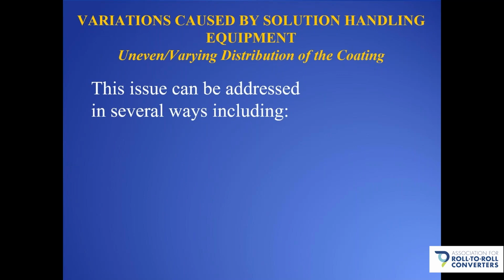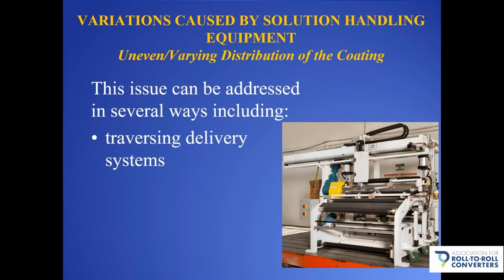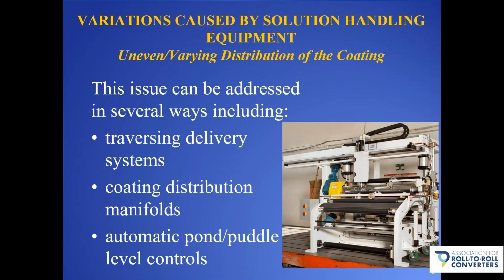So how do we address this issue? Well, you can use a traversing delivery system like you see here that moves back and forth over the top of the puddle or pond and evenly distributes the coating into it. You can use a coating distribution manifold. So maybe instead of feeding the coating to the pond or puddle from a single point, you use multiple points or even a continuous manifold to feed the coating. Another feature that you could incorporate is using automatic pond or puddle level controls to prevent the puddle or pond from surging up and down, which could cause a variation in the coating distribution or the coating laydown.